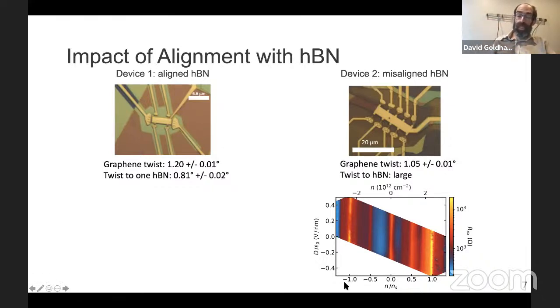-1 means we've completely emptied the moiré band. This nearly eightfold degenerate band is half filled when we do not apply gate voltage, and this is called the charge neutrality point. And on the top, I've listed units of density per centimeter squared of electrons. And what you can see here is that there are a lot of features that are all vertical and that don't change very much